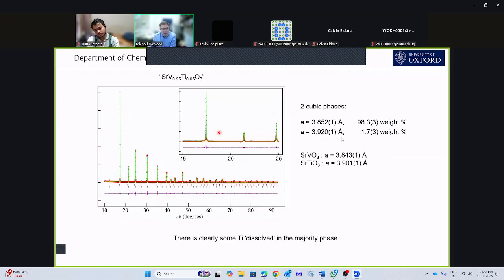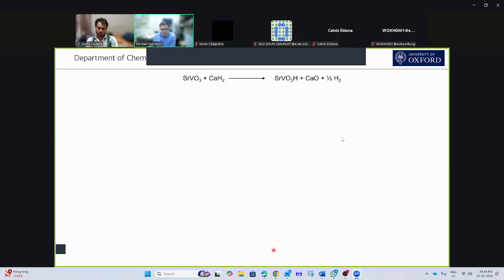But if I do this now for the 5% titanium doped material, so I arc melted and quenched it, I can get some titanium dissolved in the vanadium. We still have slightly two phases, but we do get some titanium doping. So what happens if I reduce this material? Well, what we find is something strange happens. So let me show you the progress. So what we're going to do is take SrVO3 plus calcium hydride to make SrVO2H, calcium oxide and hydrogen,